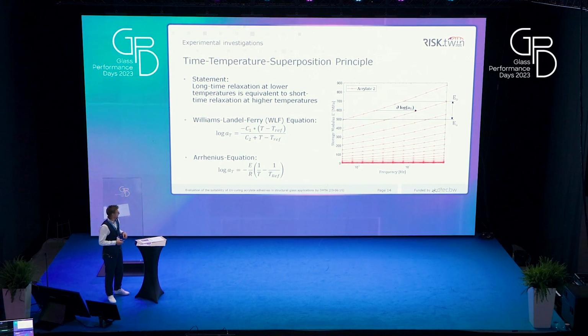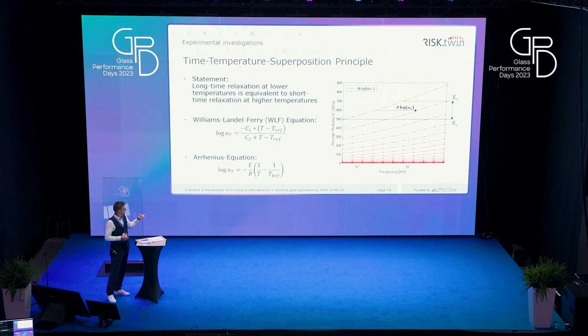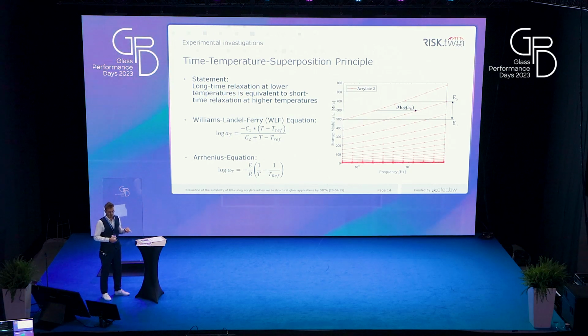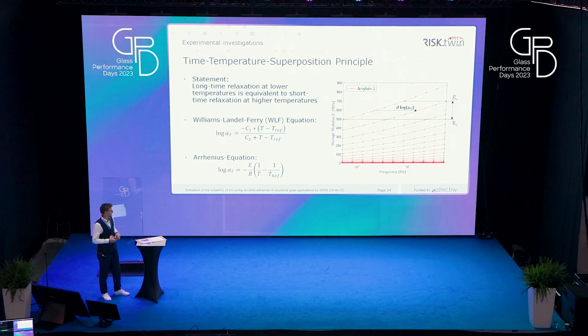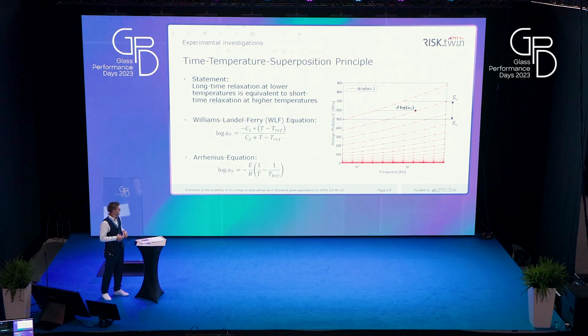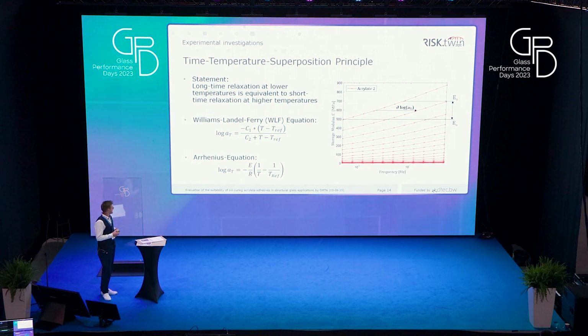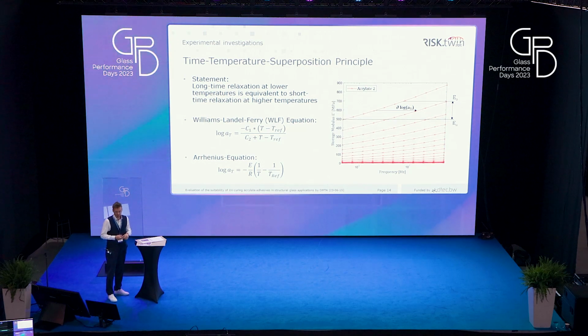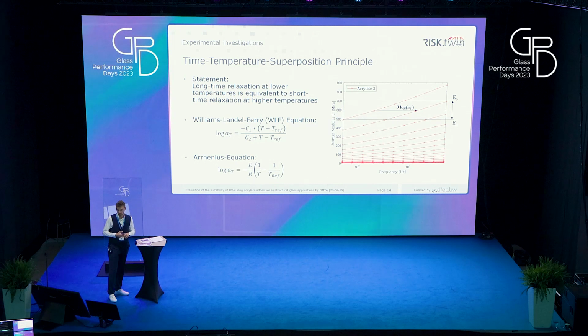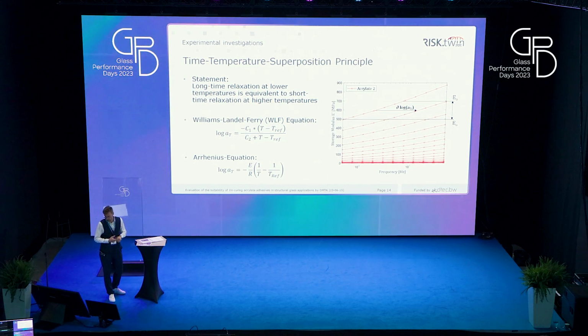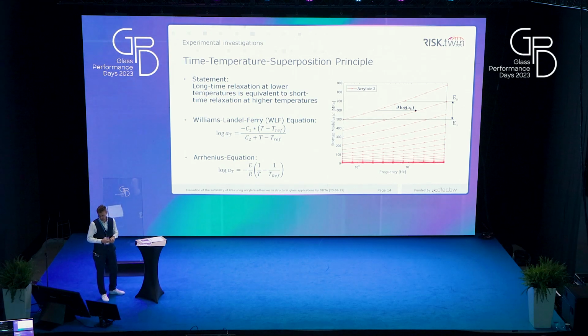So all lines that are above the line of 20 degrees Celsius are the temperatures that are lower than 20 degrees Celsius and therefore are stiffer. And now we shift them to the right until it lies exactly above the next curve. And we repeat this until we get one single curve. And the shift factor is usually got from either the Williams-Landel-Ferry equation for temperatures above the glass transition temperature or the entropy elastic region, or the Arrhenius equation, which is used for the energy elastic region.